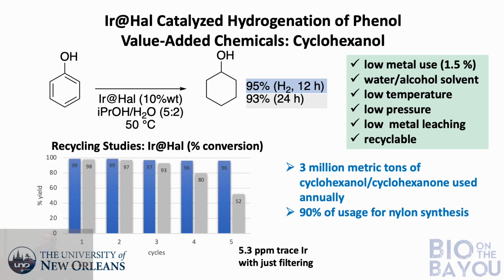Okay, and so in this case, we now have a system that's operating. We can recover the halloysite after each reaction. And we see here in our recycling systems, in the hydrogenation case, we don't lose activity after at least 5 iterations. So we can keep recycling the catalyst and essentially we recover the metal. Also, what's important from a potential use in pharmaceutical applications is that we only see about 5 ppm of trace iridium in the products. That's just after filtering. That's not doing any other type of purification. And so clearly we can make pure materials, very clean.